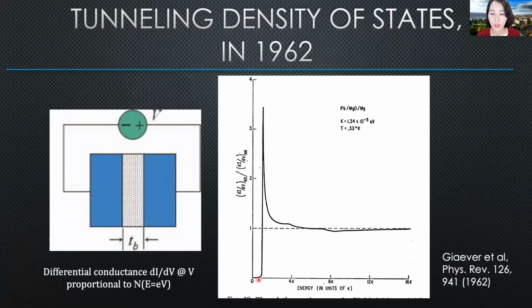They found this suppression of the density of states and a sharp peak, but it's not only those features. When you have a single curve, theorists have not been able to understand even the subtle features and confirm that this is evidence that the BCS mechanism of phonon-mediated superconductivity is in play.